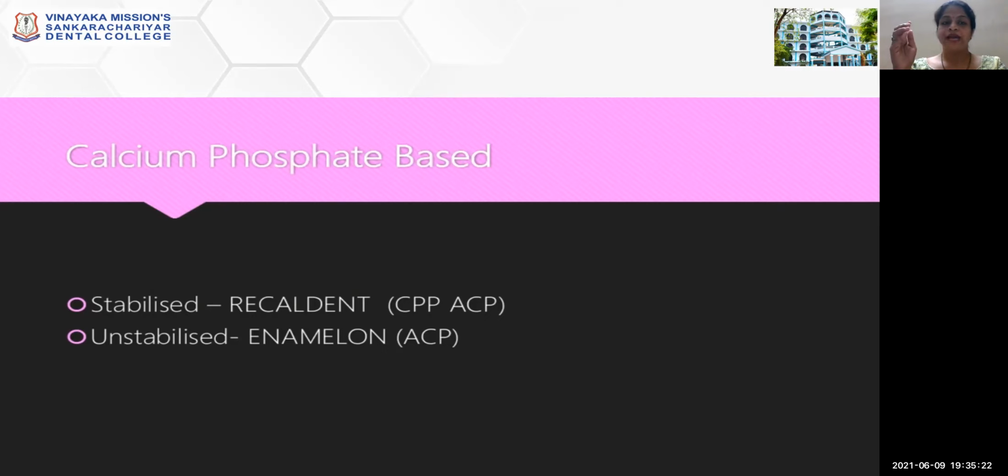As the calcium salts mix with the saliva, they dissolve, releasing calcium and phosphate ions. The mixing of calcium ions with phosphate ions to produce an ion activity product for amorphous calcium phosphate that exceeds its solubility product results in immediate precipitation of amorphous calcium phosphate, that is ACP, or in the presence of fluoride, ACFP, that is amorphous calcium fluoride phosphate.